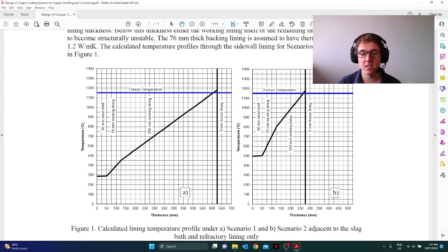This is for a simple planar system. You can see you've got a 50mm steel shell, a backing or insulative lining, then your working lining. They've got different bricks for these; generally a mag chrome brick for non-ferrous pyrometallurgy, and you have other brick systems for other commodities. The insulative lining won't resist your slag components. So in this particular case, there are scenario 1 and scenario 2.